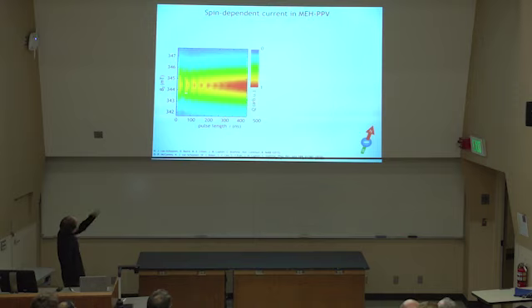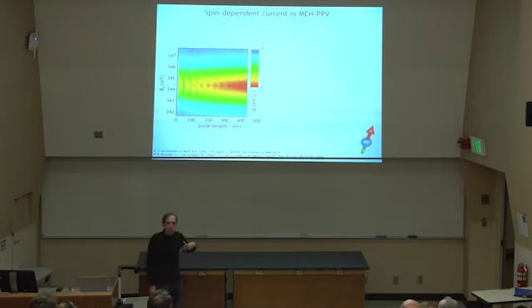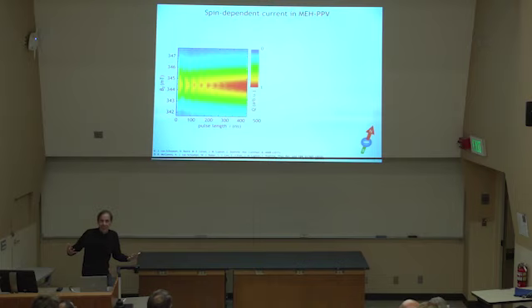And here you see again, also as a function of magnetic field, a response around a particular resonant magnetic field. You don't see a response outside of this. If you look at the color scale, that corresponds to 0 charges. But then you see on resonance some sort of dynamics. And that is now the reflection of the coherent spin dynamics of these paramagnetic systems that you excite there, whatever they are.